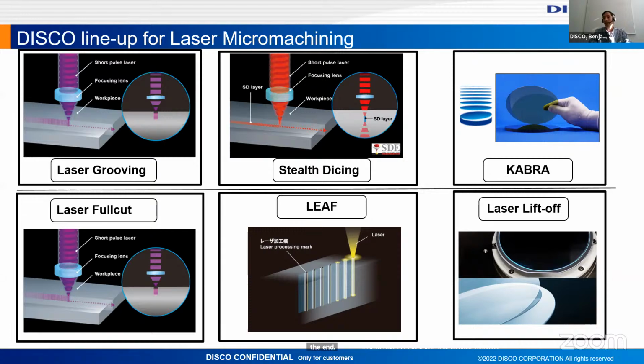Last but not least on that slide, we have the laser lift-off, mainly gallium nitride grown on a sapphire substrate, and then you want to lift off the GaN. So we use a laser to focus precisely on the interface between those two materials, and then you can lift off the gallium nitride layer from your bulk material and transport it wherever you want to have it.